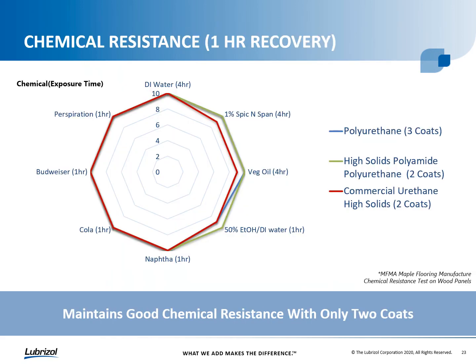Here we're comparing the chemical resistance between these different polyurethane systems. In this particular case, we were looking at the MFMA, or Maple Flooring Manufacturers Association's, chemical resistance test on wood panels. There's a variety of different chemicals you can see here, with varying 1-hour or 4-hour exposure times, and then being rated after a 1-hour recovery period. Here again, we're comparing 3 coats of the traditional polyurethane system to just 2 coats of the high solids polyamide polyurethane, and then 2 coats of the high solids commercial benchmark product.